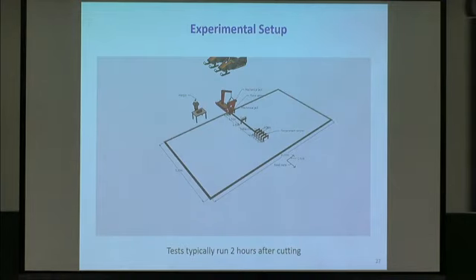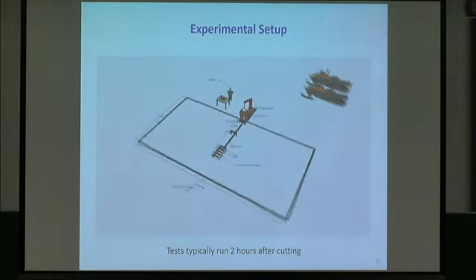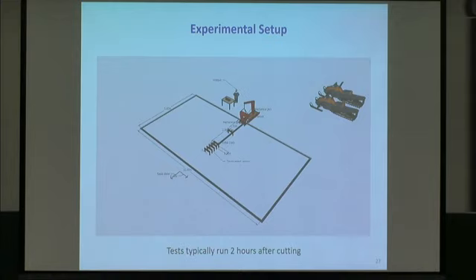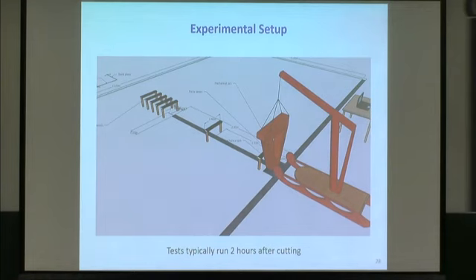A test was typically run within about 2 hours after cutting here. And you can also wonder why we could be so effective. I'll come back to that. Here you see this from another perspective. And the instrumentation.